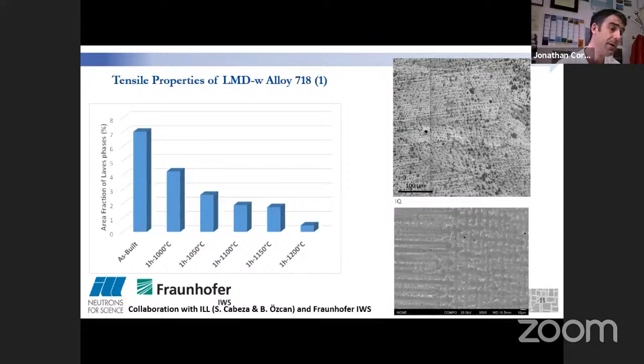First of all, here you have a typical microstructure in the as-built state. This is an EBSD map with an image quality observation map, and here, backscattered imaging mode, in which in the as-built state we can observe the dendritic type structure, and all the white particles, or black ones here in IQ mode, correspond to Laves phases. That's something known in the literature to be detrimental to the properties. We will see that's not really obvious afterwards, but it is usually considered detrimental, especially for toughness.